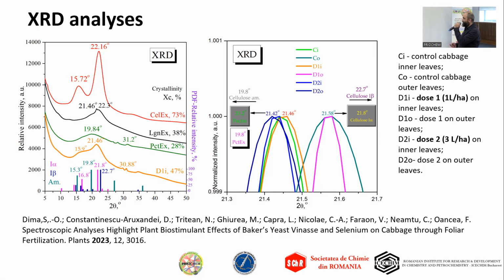Regarding the structure of cabbage, it was firstly reported as cellulose 1 alpha and pectin. The difference between cellulose 1 beta and 1 alpha: 1 beta consists of two chains in a monoclinic arrangement, and it's more resistant, while cellulose 1 alpha is one chain. It's more flexible and can be related to the edibility aspect, being also metastable and degrading more easily than cellulose 1 beta.